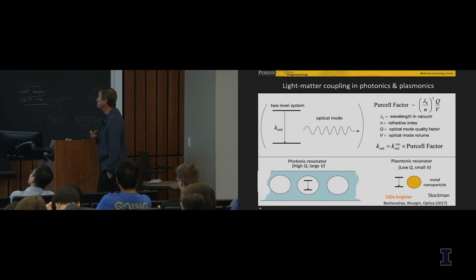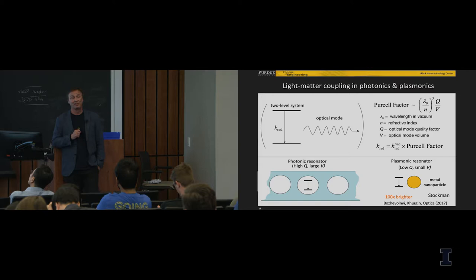Most teams take this approach, using cavities with a very high quality factor. For example, a defect-based photonic crystal has a quality factor which could go up to 10 to the 8. But the volume in this case is limited by the diffraction limit, because that's the way a photonic crystal cavity works, and that's the smallest possible conventional cavity. But the claim here is that the higher the Q, the slower the response. You pay the price. The higher the quality of your resonating system, no matter what, the slower the response would be.